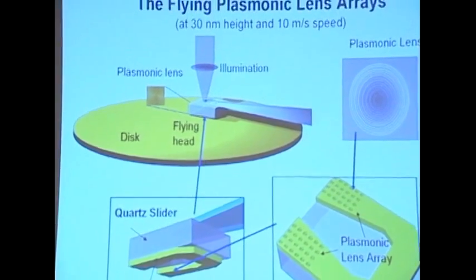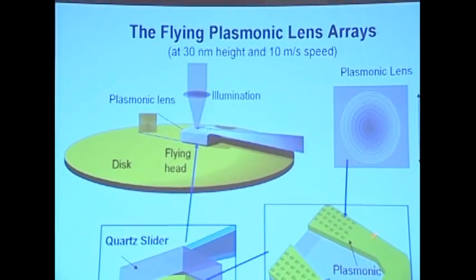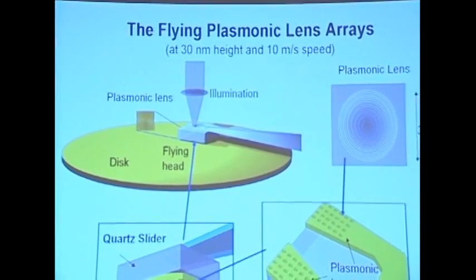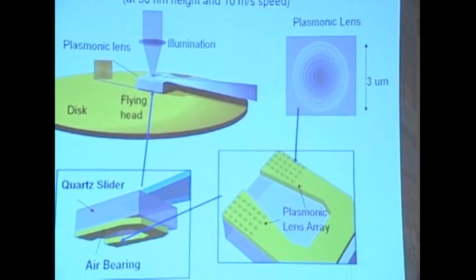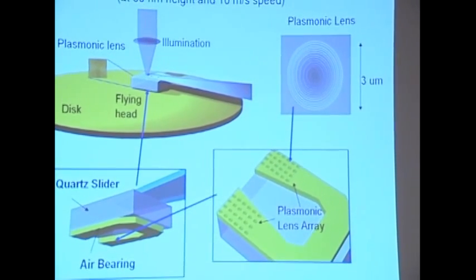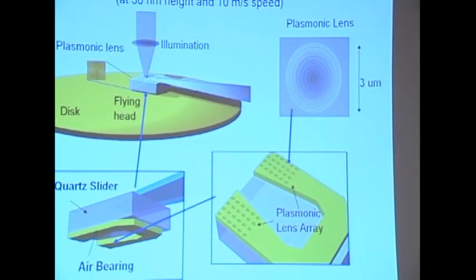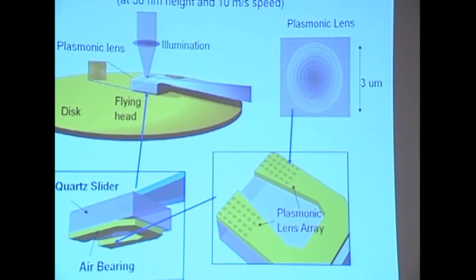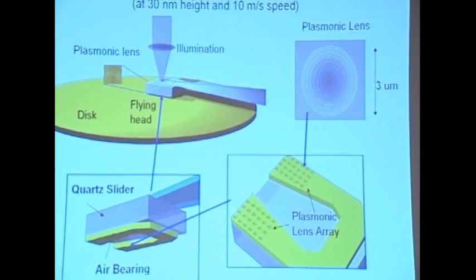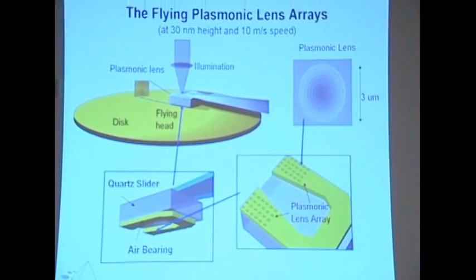If you scale everything up, with a millimeter-size flying vehicle, it's like an airplane flying at 6 inches high over the tip of the grass, conformally. Right now our tests show that flying at 10 meters per second is stable to about 1 nanometer plus or minus. So it's a very stable flight, and of course the surface has to be relatively flat for lithography.